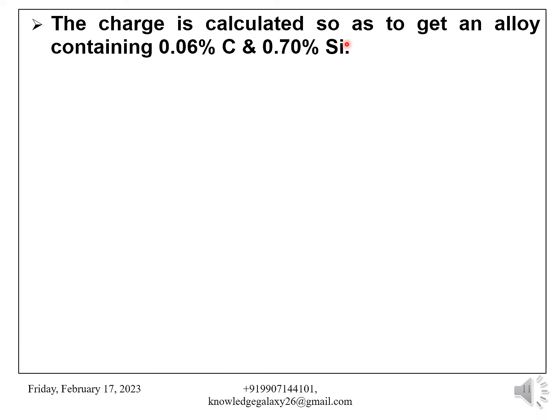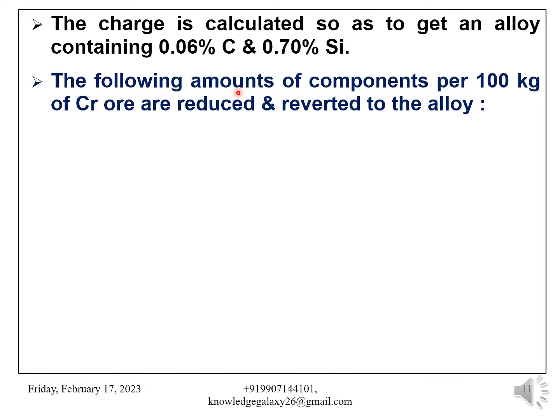The charge is calculated so as to get an alloy containing 0.06% carbon and 0.70% silicon. The following amounts of components per 100 kg of chromium ore are reduced and reverted to the alloy. Chrome: 100 × 0.53 × 104 / 152 × 0.82 = 29.74 kg.